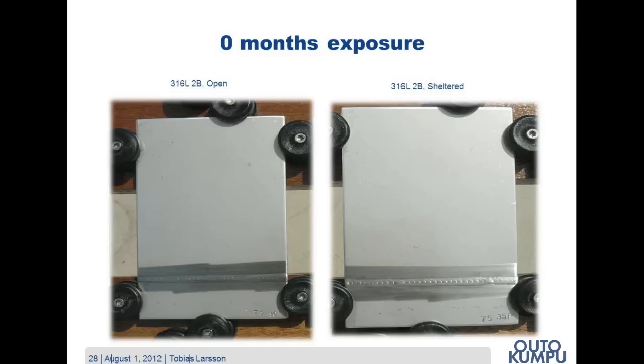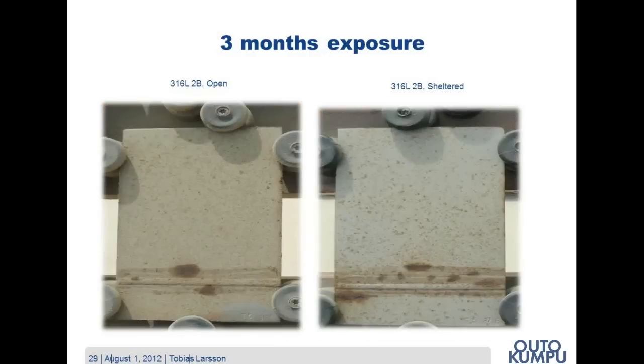Here you can see the austenitic grade 316 with a cold rolled finish, so-called 2B. This is the same grade as we saw earlier that performed well in a European marine environment after 50 years exposure. And this is the same sample after 3 months. It does not look pretty. So actually this grade performs worse in a Middle Eastern marine environment after 3 months than it does in a European one after 50 years.